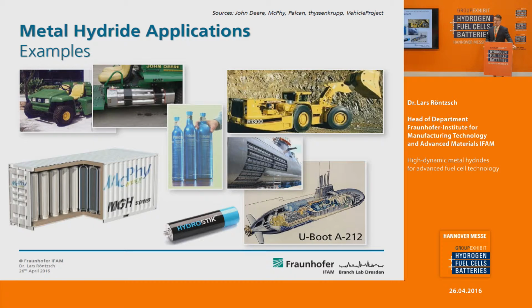And one of the crucial things about metal hydrides is not only capacity and kinetics of the reaction, but also thermal management and heat transfer, because very often these are the bottlenecks in terms of technical use of metal hydrides. So very often tube bundle reactors are used where a hydride is located in the center of a pressure pipe and surrounding you have a heat transfer fluid or a gas flow where heat is being delivered into the hydride to set up the hydrogen flow, or during the hydrogenation, we will have the exhaust heat that is being produced